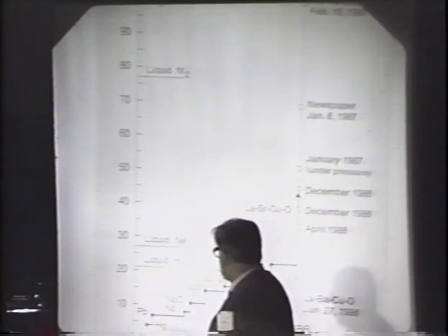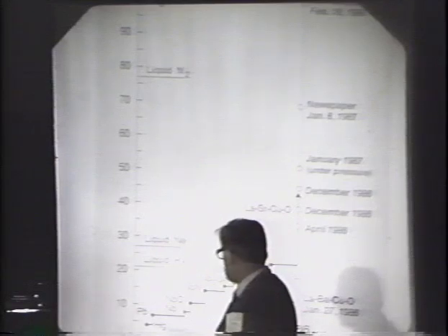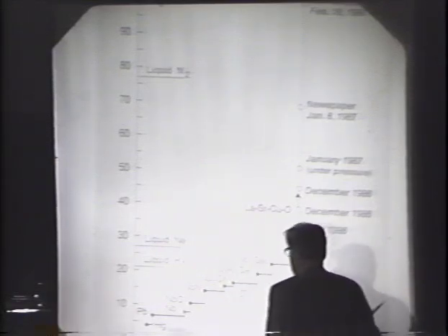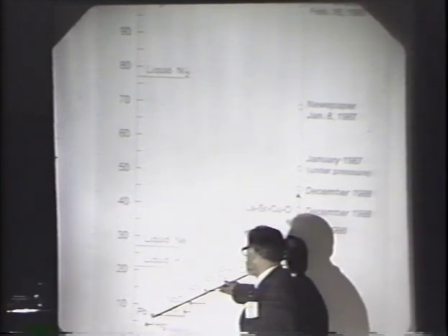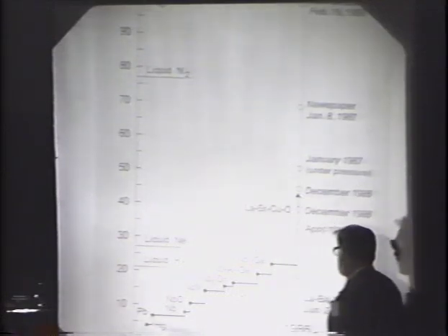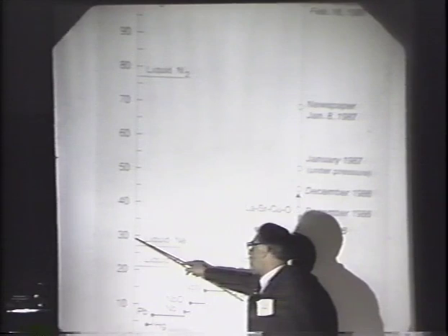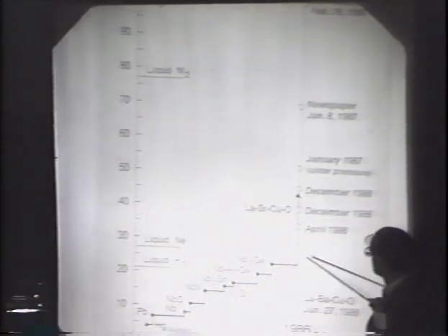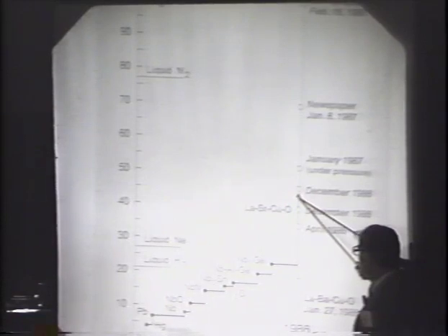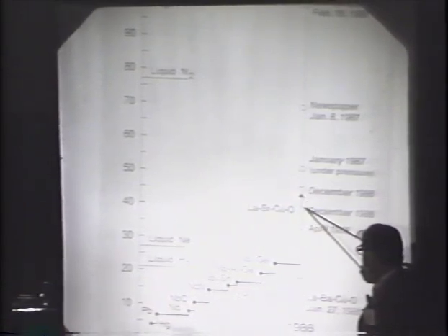Now, what has been achieved? I have plotted here transition temperature versus the years where they have been achieved, starting from the discovery in 1911. And you can see from that graph that if you would extrapolate more or less linearly as a function of time, you would expect that by 1989 you would have reached about 30 degrees Kelvin. Instead of that, already by the end of last year, one had exceeded this extrapolation by quite a bit, and by now,